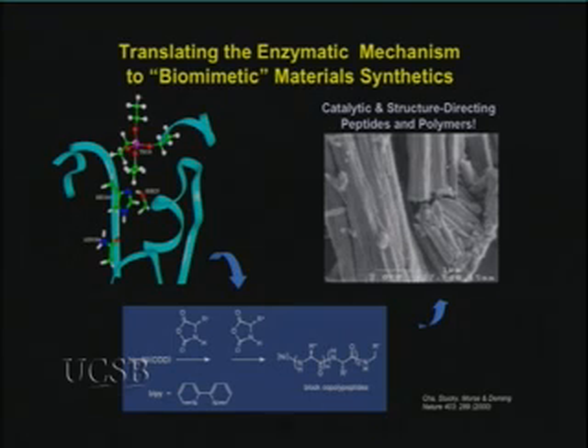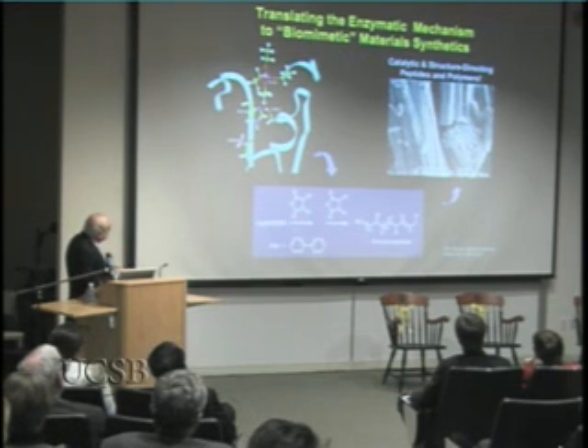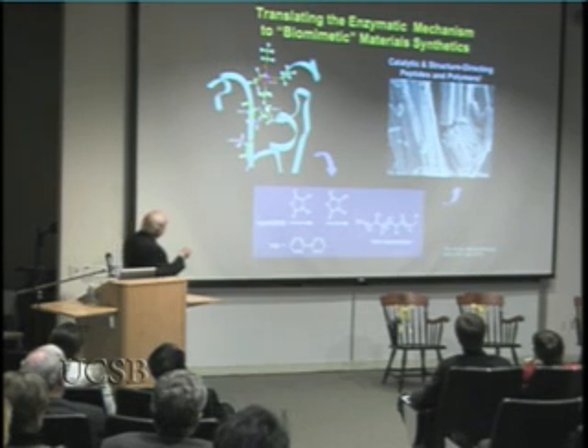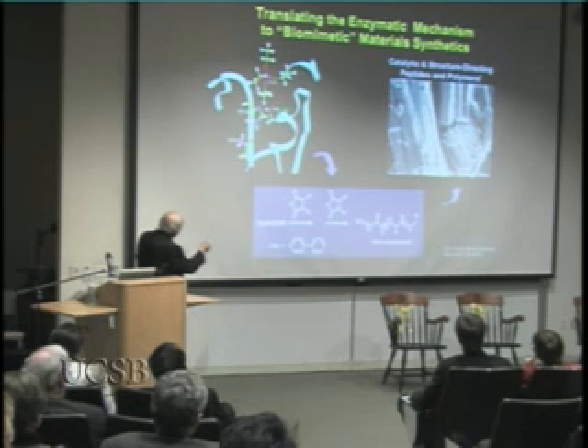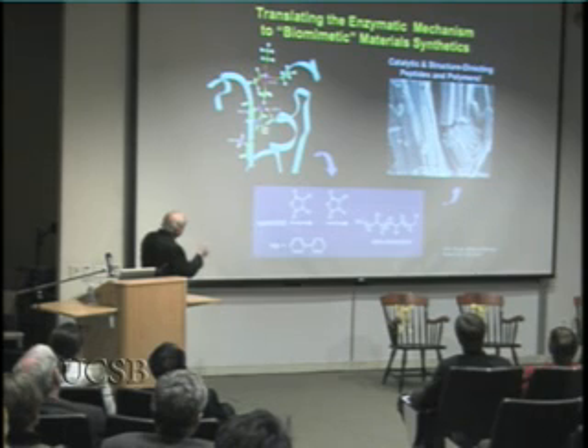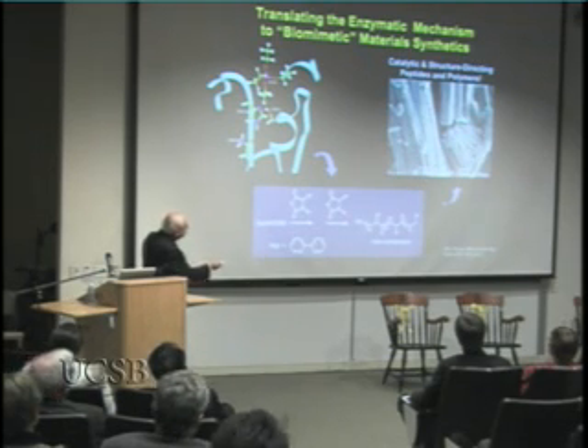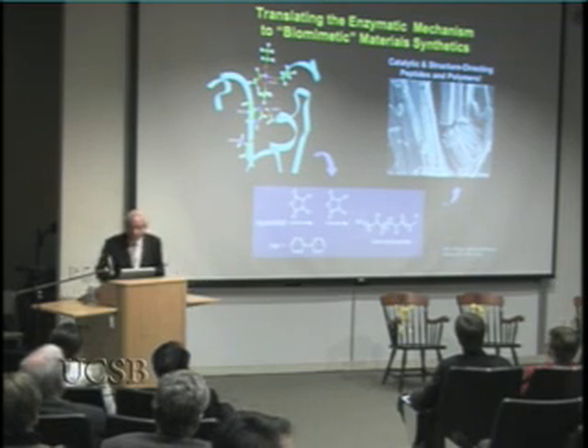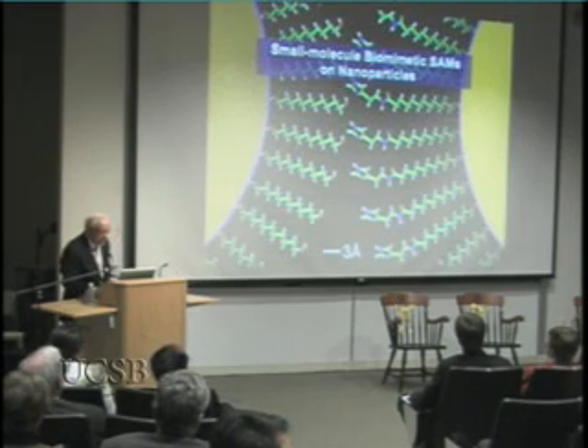To translate and test this mechanism that we discovered to the kind of biomimetic material synthesis that Matt described, we began to make synthetic polymers, peptides and non-peptide polymers, that incorporate those active groups that we identified as responsible for the catalytic mechanism, and found, sure enough, when we make synthetics, they also will self-assemble and catalyze the synthesis of structure-controlled silica or glass, or in some cases, semiconductors.